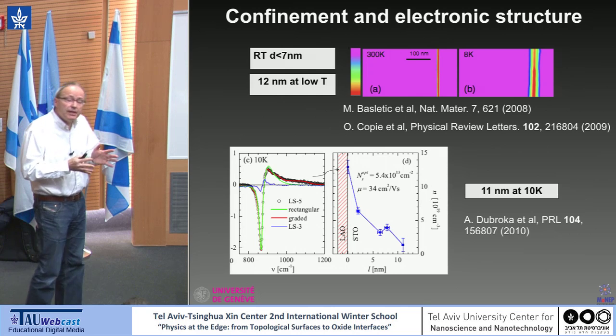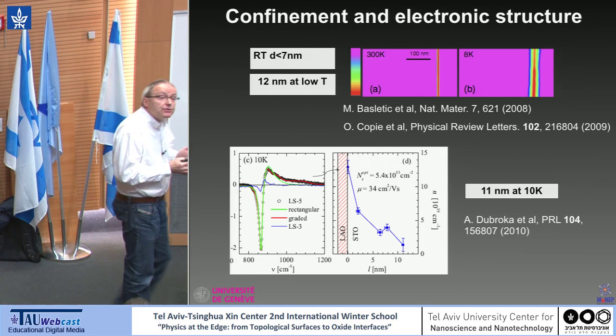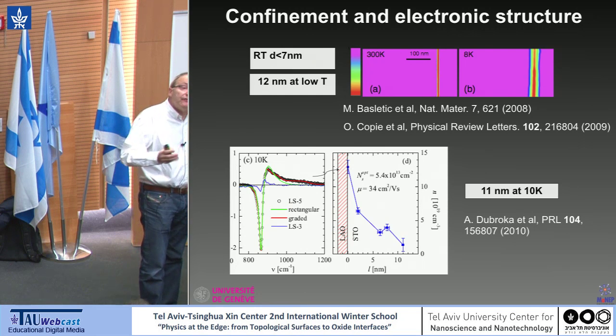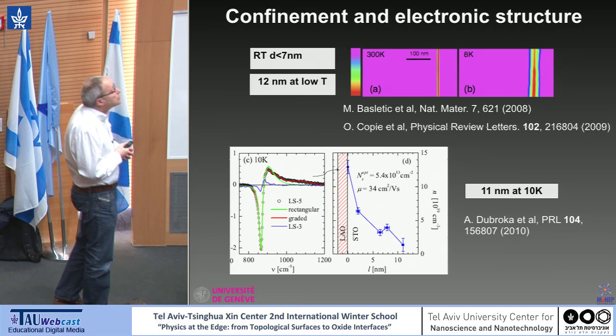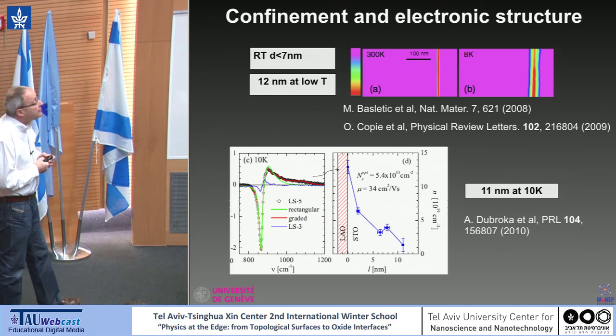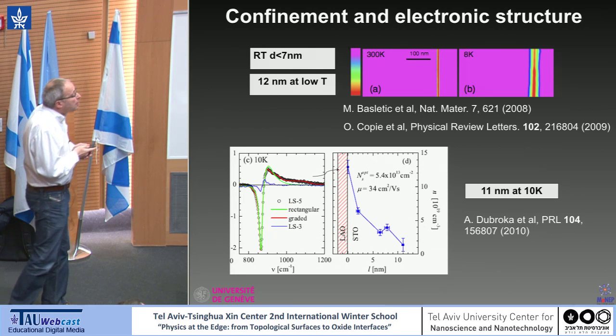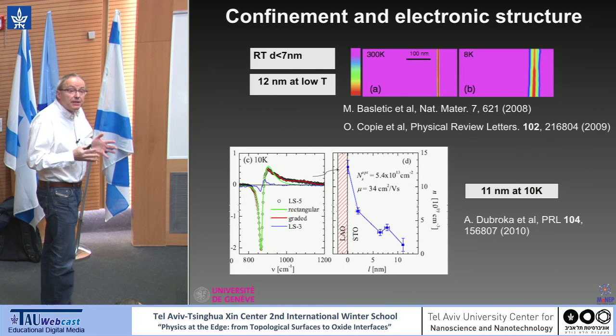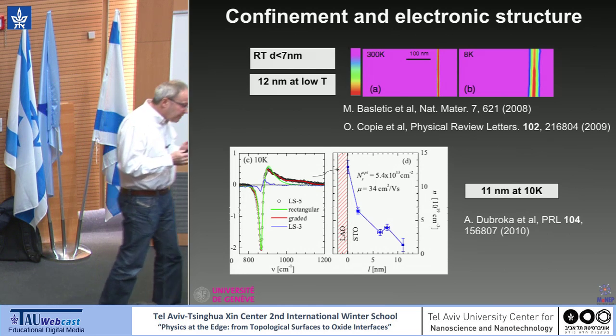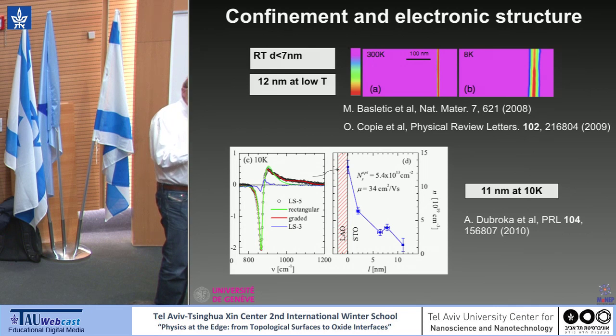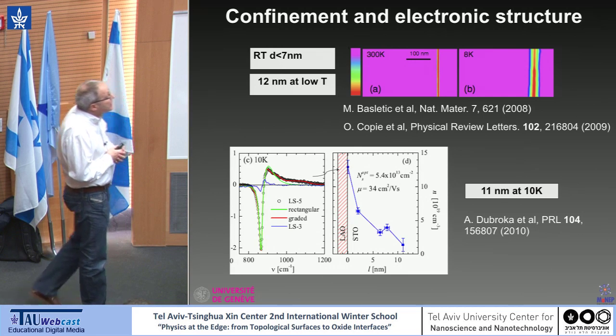This is due to the dielectric constant of strontium titanate, which is diverging as we go to low T. Strontium titanate is nearly ferroelectric. And the thickness which was measured was about 12 nanometers. In Fribourg, in the group of Christian Bernhard, they used optical spectroscopy, and they were looking at a mode which is confined by the width of the conducting layer, a Berreman mode.